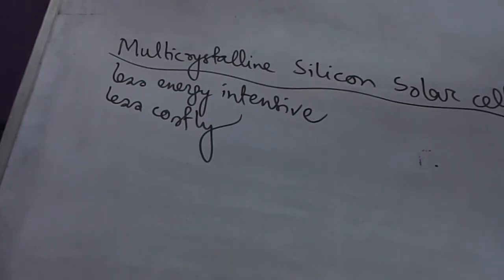Commercial multicrystalline solar cells have efficiencies in the range of 10% to 14%. The first two steps of manufacturing, up to the production of polysilicon, are the same as explained above for the case of single crystalline cell. The polysilicon thus obtained is melted after proper doping and an ingot of multicrystalline silicon is produced.